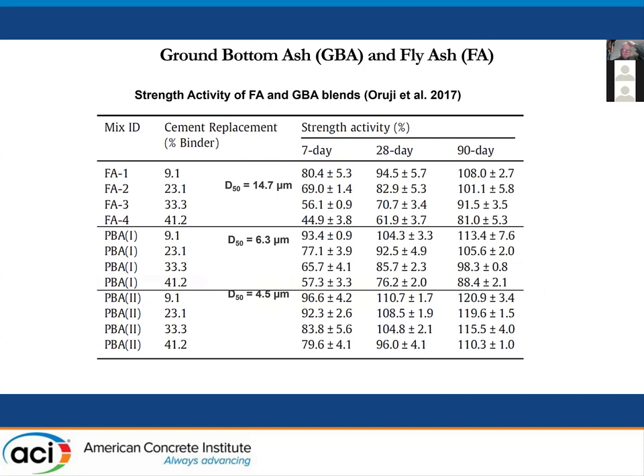Here's some other work, again showing fly ash with an average particle size of 14.7 microns, and it shows the strength activity at 7, 28, and 90 days. And you've got bottom ash ground to two different finenesses here. And you can see as you grind it finer, you get higher strength activity at all ages.